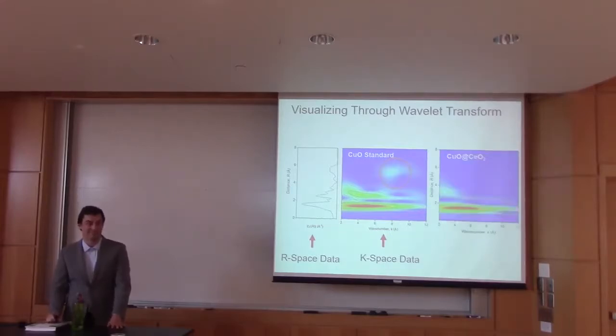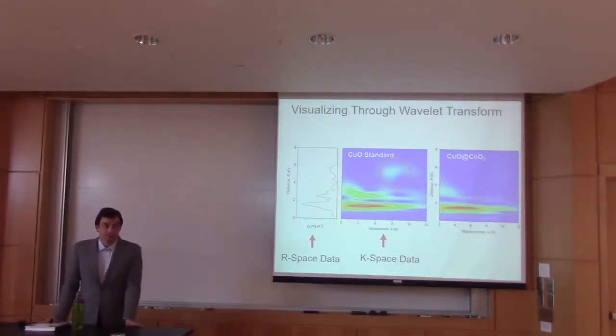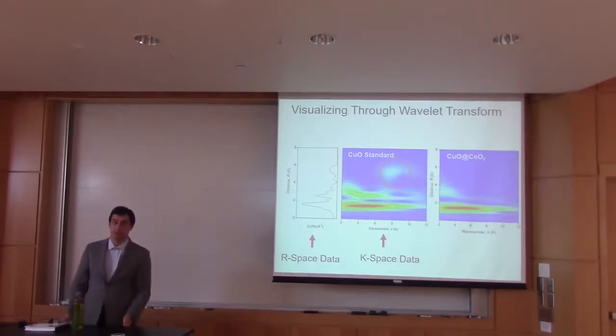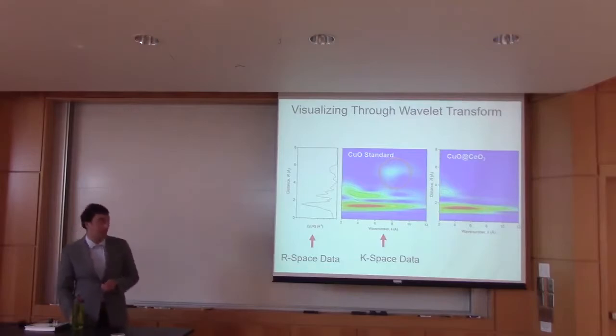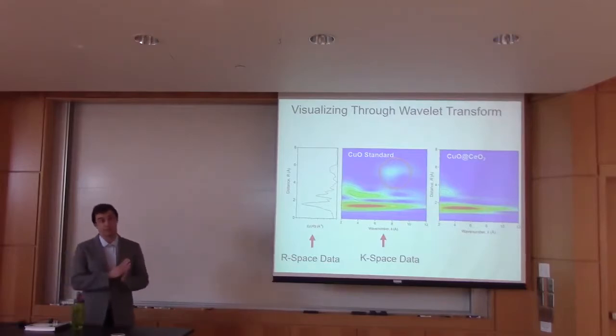Graham? Do you ever see anything with copper cerium distance, or are you not within the range of that ionic radius? Yeah, so the energy levels to look at these metals vary dramatically. And I know for cerium we can't look, so we're using the K edge for the copper, and you have to use a different edge for the cerium. And this is all being predicated by the previous XAFS results from the last catalyst, which they didn't collect cerium data for. I think the issue with that is looking at overlap of edges and getting really messy, hard to interpret data. I don't know if that's possible either, but it might be.